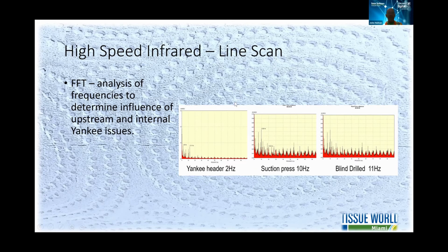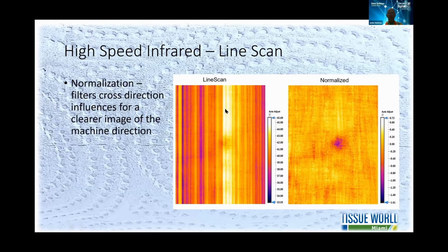Here's another image where the line scan is normalized. So you can take out the cross direction variation and create a normalized version which shows you more clearly the machine direction variation, of which we more clearly see this spot in the middle.